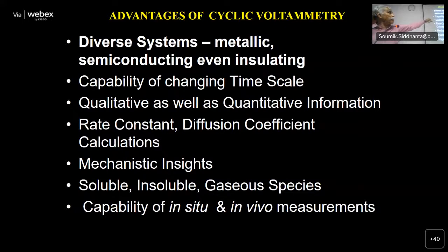Capability of changing time scale is very important because you have competition between diffusion and electron transfer. By changing the scan rate, meaning sweep rate, from millisecond or microsecond to several hours, that is where it is possible. Capability of change in time scale I mentioned. Qualitative as well as quantitative information can be obtained. And if you do quantitative analysis, rate constants can be calculated from irreversible and quasi-reversible systems. All the thermodynamic information can be obtained from reversible systems, which means equilibrium constant, maybe the entropy, enthalpy, all that can be obtained, even solvent contribution can be calculated.